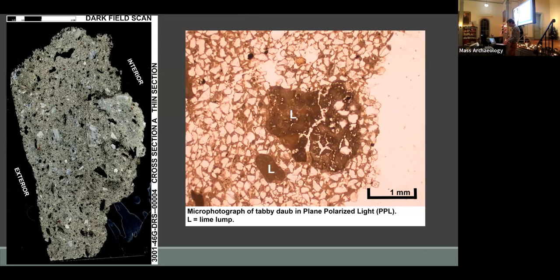But few factors affected the final quality of tabby more than choice of mix. Now, Thomas Spalding, who I've mentioned a few times before, published a recipe involving equal proportions of lime, sand, oyster shell, and water. However, when people went to recreate that recipe, they found that his recommendation for water was too much, and it actually led to poor quality tabby. So tabby mixes from Beaufort have been observed to consistently contain more shell, with one recipe calling for 1 part lime, 2 parts sand, and 4 to 6 parts shell.